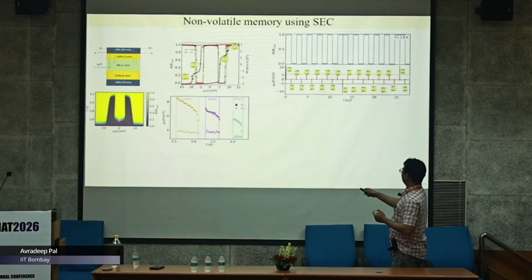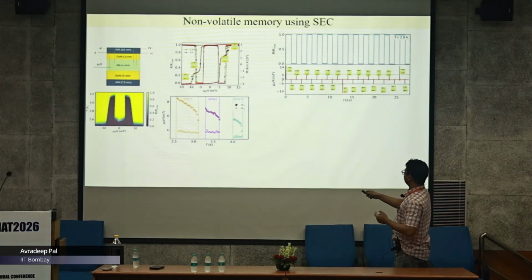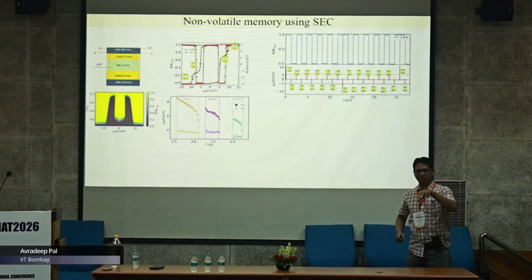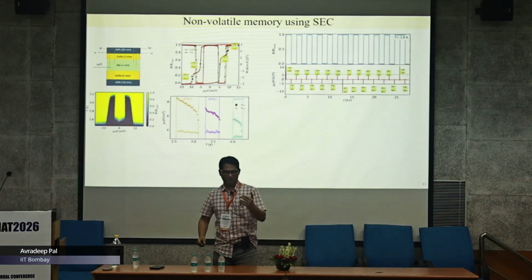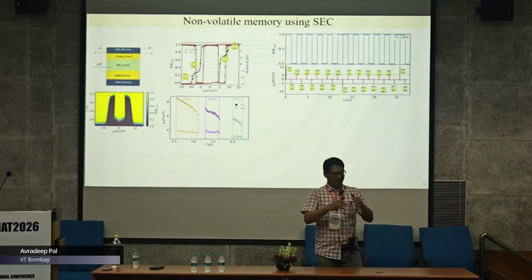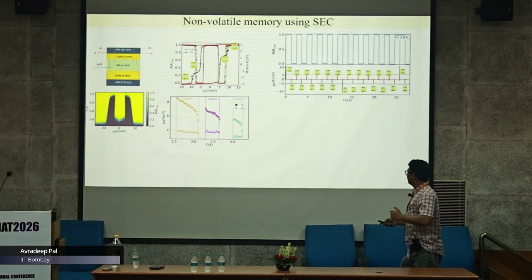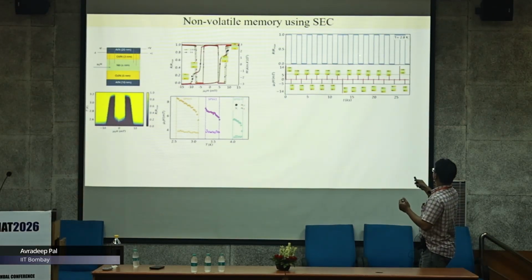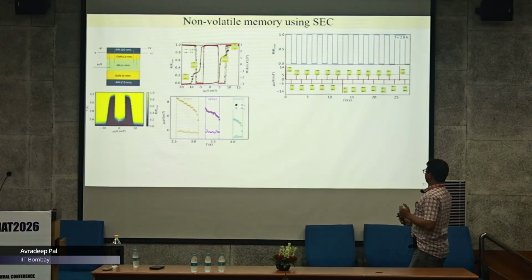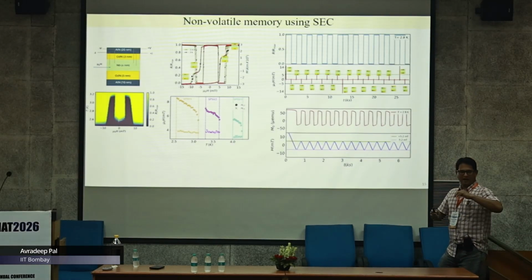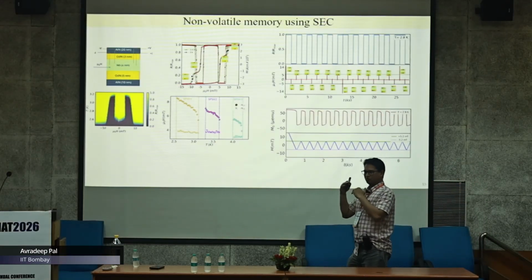So this is the soft ferromagnet. I'm doing the full loop of the soft ferromagnet, but I'm doing minor loops of this hard ferromagnet, which is switching over here. So when you do several minor loops of a ferromagnet, what should happen is that there should be domain nucleation, okay? And the magnetization should change, and it should not be so easy to hold on to these perfect superconducting and resistive states. But because of that superconducting exchange coupling, the actual magnetization state holds.